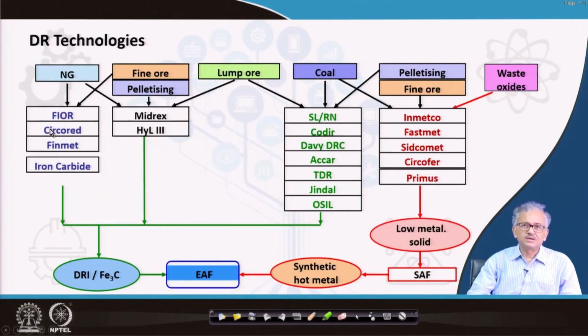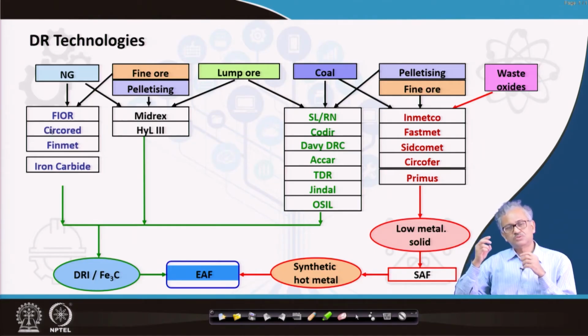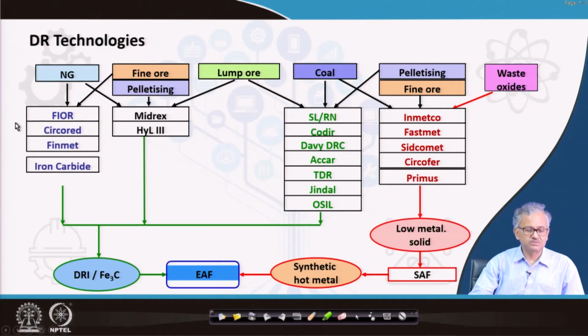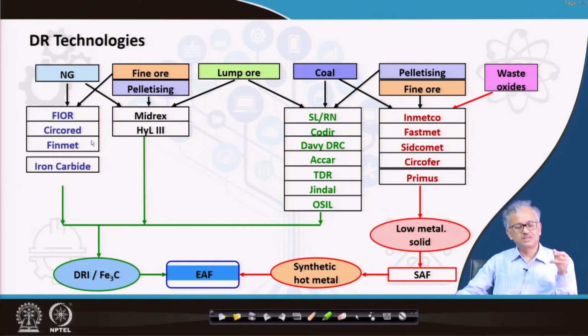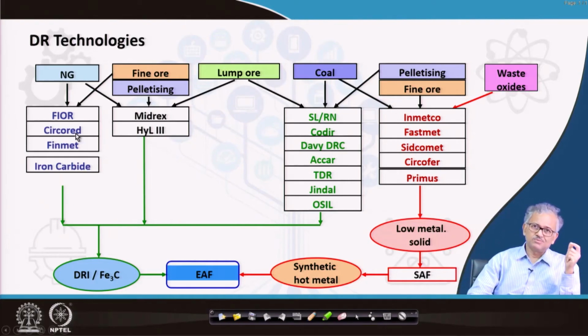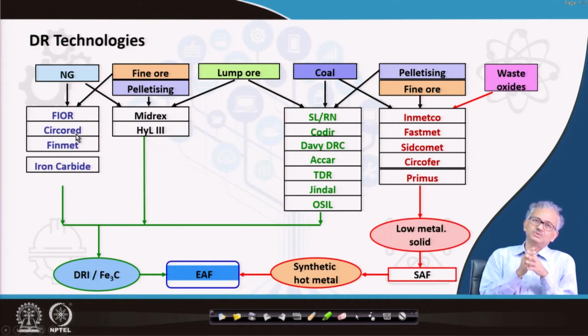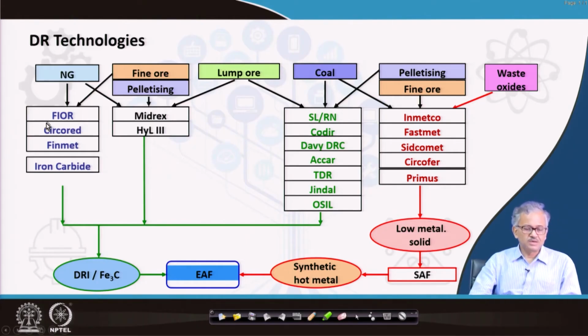So the major invention in the Circored process is that they do the reduction by reforming the natural gas to hydrogen. So this reduction is based on hydrogen only, not CO. You take the natural gas and reform it such that you get only hydrogen, and then the reduction takes place in the hydrogen atmosphere only. With hydrogen you can reduce at a comparatively lower temperature, and as a result your sticking problem will be less. So this is the speciality of the Circored process. Finally, whatever the product is, it is briquetted, hot briquetted iron, and then you can charge it into the electric arc furnace.